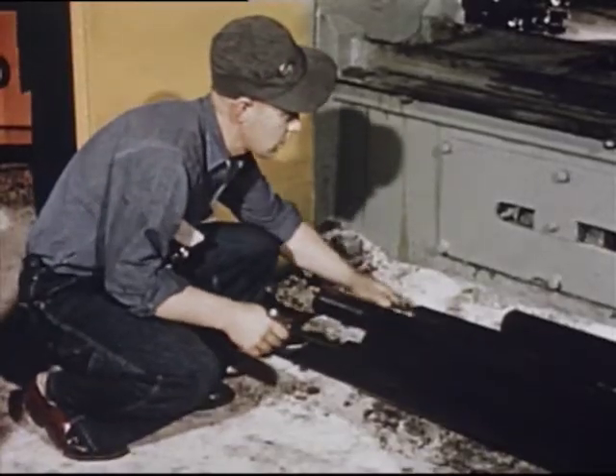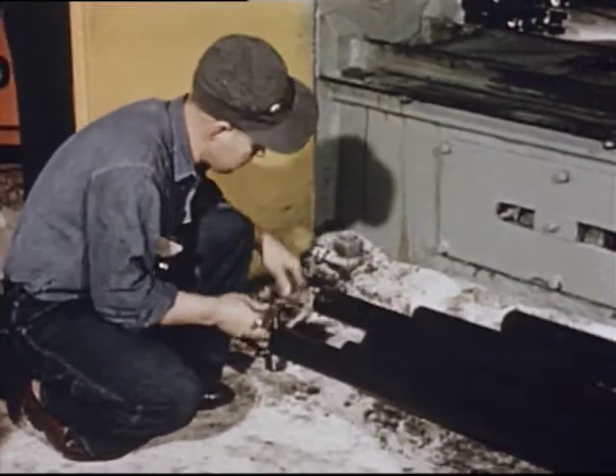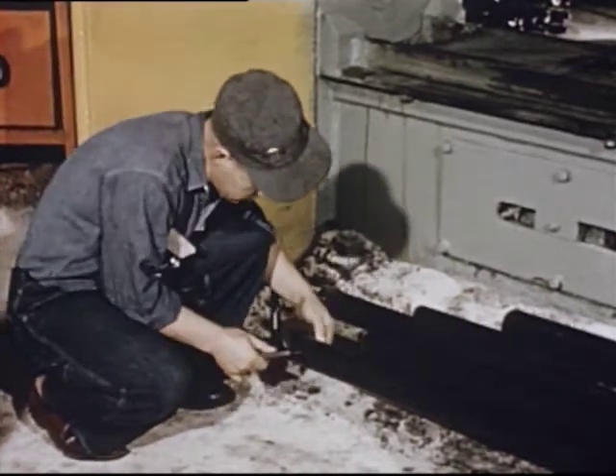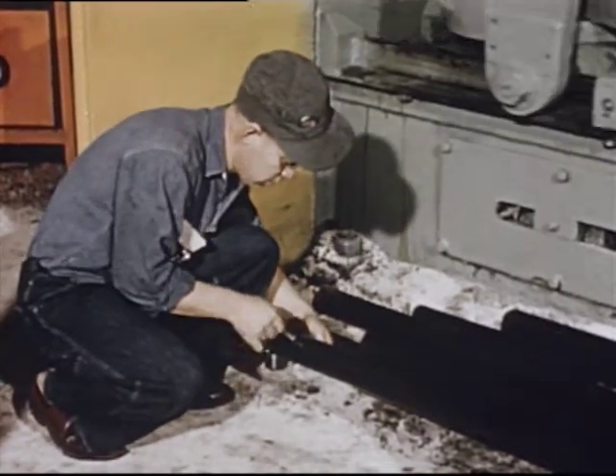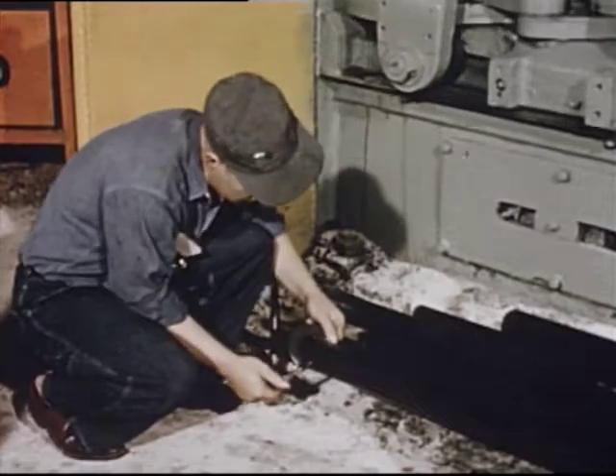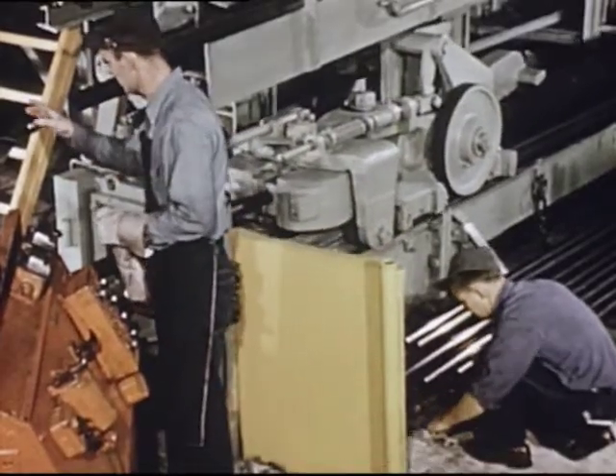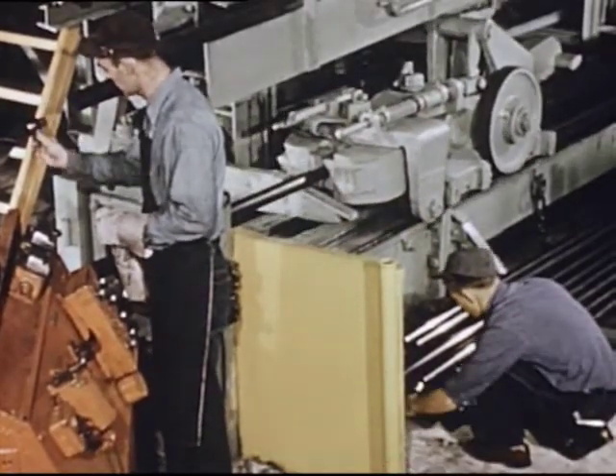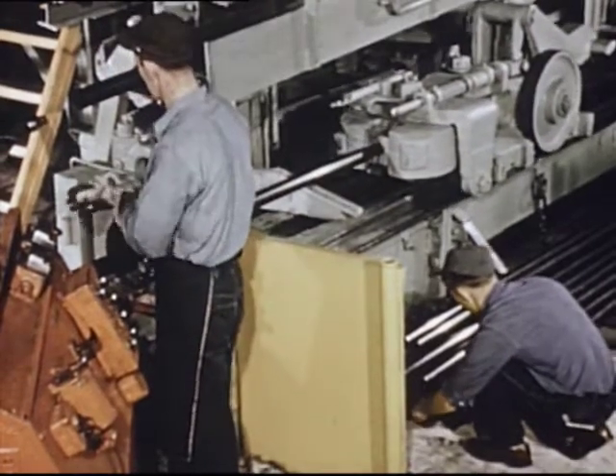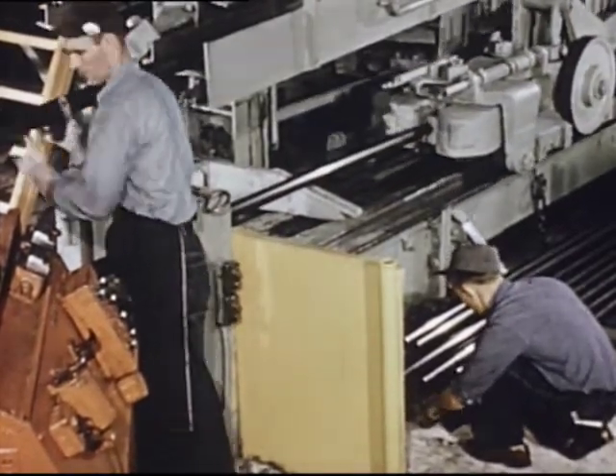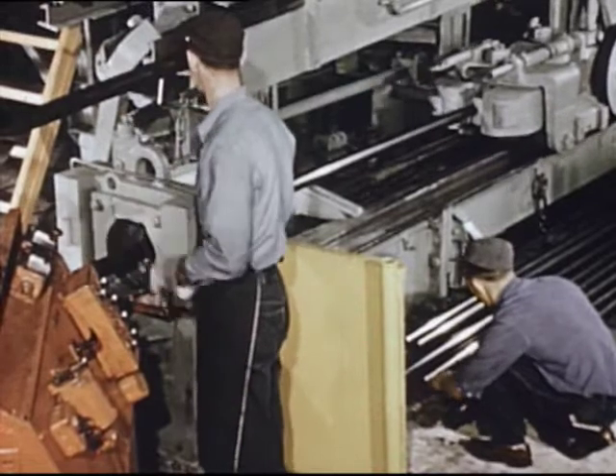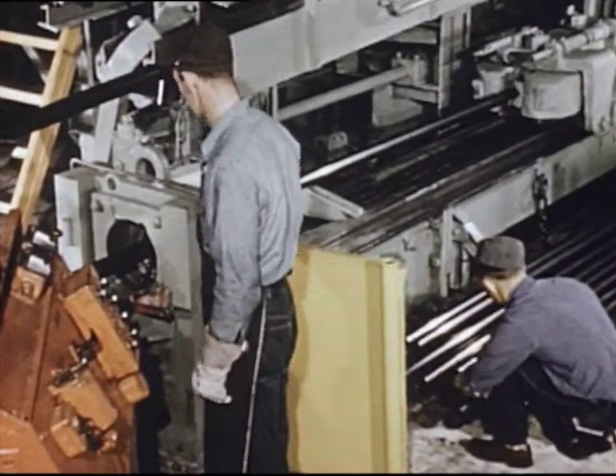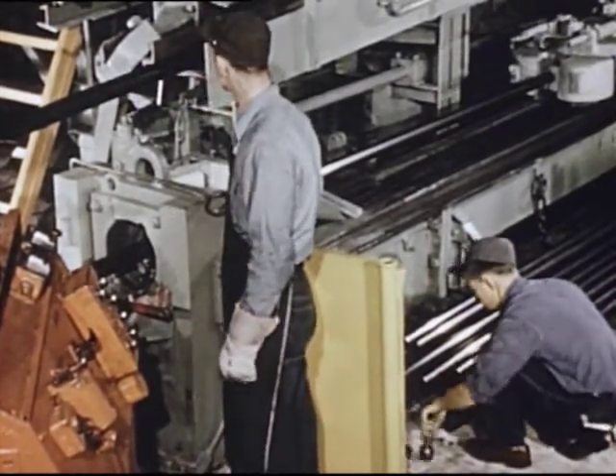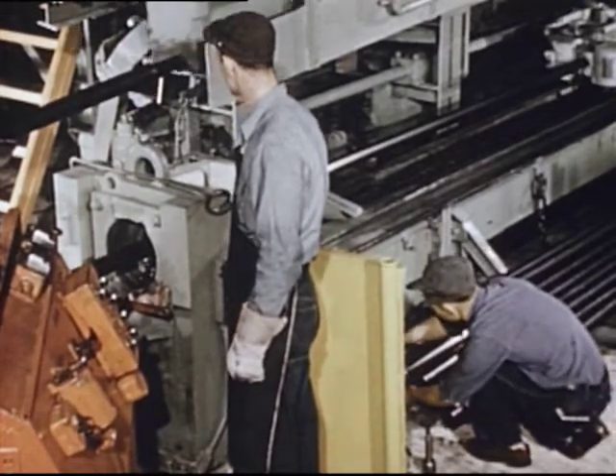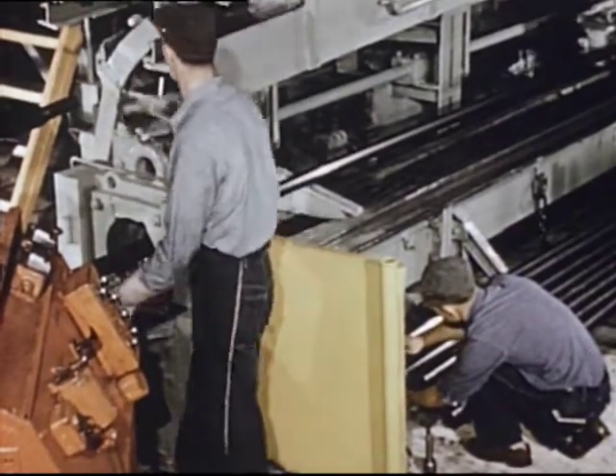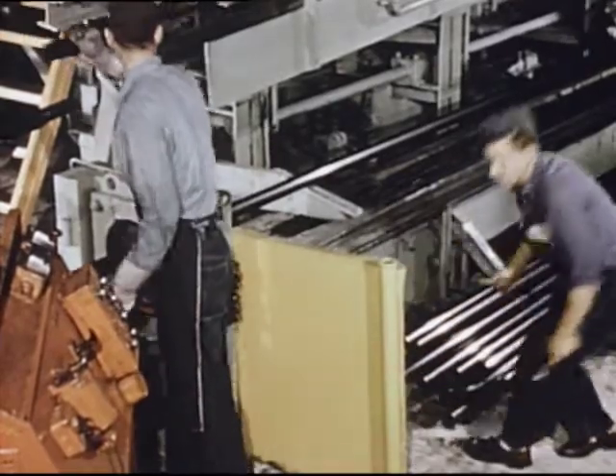For further control of the quality, Michigan Seamless uses trained gaugers to check for all quality factors on every cold draw pass. Since the cold drawing process stresses the steel beyond the yield point, only full-strength, high-quality tubing can be successfully drawn. This process causes severe work hardening, and in general, tubes must be annealed between passes. Such anneals are followed by the complete pickling and lubricating practice we saw before.